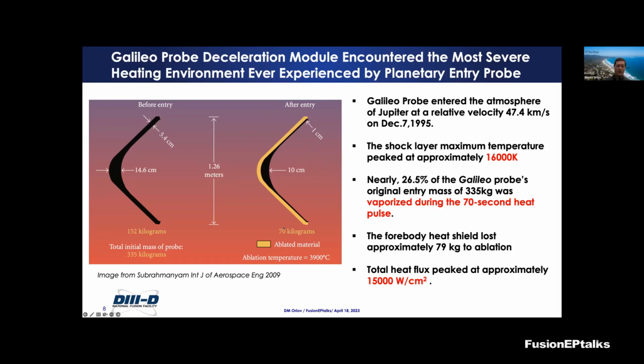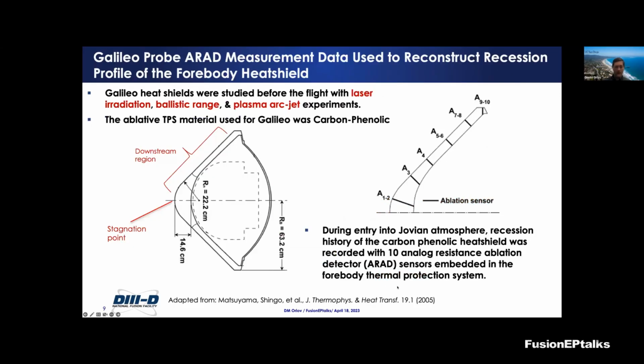The mass went down to 70 kilos. The heat shield lost about 79 kilograms of ablation, and that happened over 70 seconds of the entry. That was such an extreme heat flux that peaked at about 15,000 watts per square centimeter.